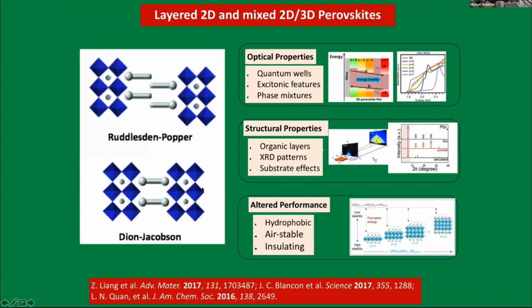So I told you that the field is moving towards more complex structures like these mixed 2D, 3D, okay? Here you have a so-called n equals 1. You have one layer that's just 2-dimensional. And then here, on the 2-dimensional, you put one additional layer of octahedra, and so build up a 2D, 3D system. And actually, these are very interesting systems for optoelectronics. They have quantum wells, they have excitonic features. They also are strong light emitters. And so there's a lot of interest in these 2D systems.